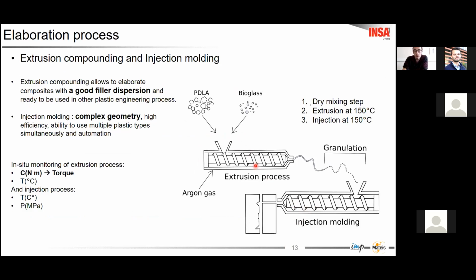So the composite was obtained by extrusion and milling the filament to obtain a compound with an excellent filler dispersion.